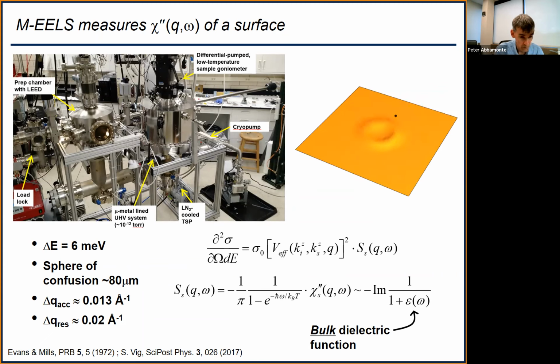For low energy electrons, our electron kinetic energy is typically 50 eV. The multiple scattering occurs overwhelmingly in the elastic channel. Meaning the electron comes in, diffracts many, many times, scatters inelastically once and then departs the sample. In that particular limit, and this was worked out in papers by Doug Mills, who spent a big part of his career on this,